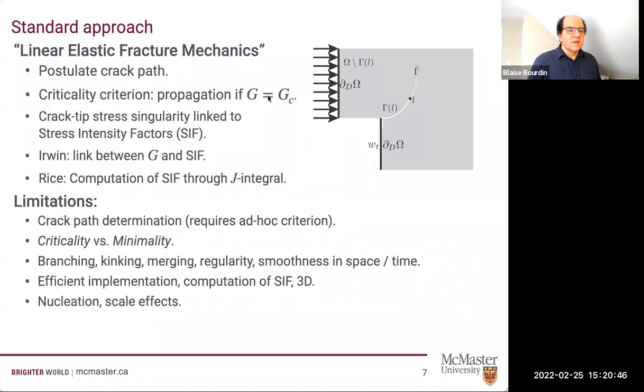Well, the way to compute G, it typically has been to link the elastic energy release rate with the singularity of the elastic displacement of the crack tip. That's the stress intensity factor. And that was done by, among others, Irwin, that links these two. Then find a way to compute this stress intensity factor. This is usually done through something called a J integral by Jim Rice and so on. This is a great theory in the sense that it really led to major accomplishments, but it still has many